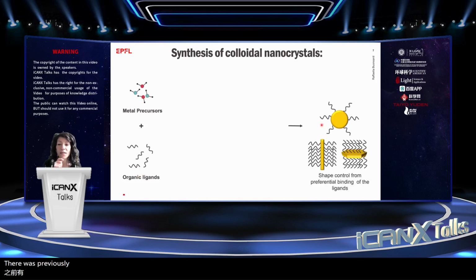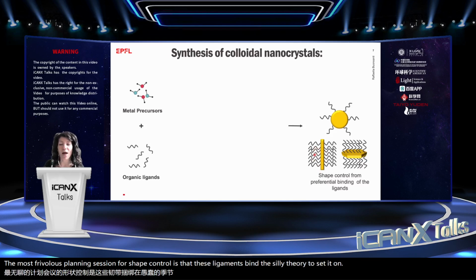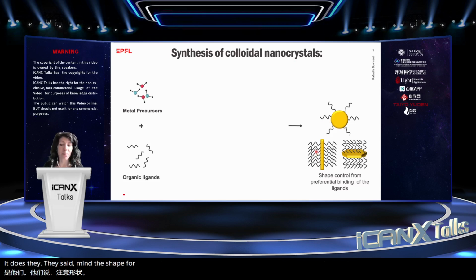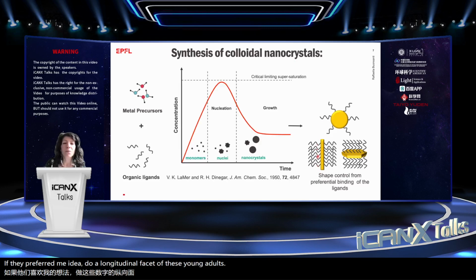The most trivial explanation for shape control is that these ligands bind selectively to certain facets, and thus they determine the shape, for example, as nanorods, if they preferably adhere to a longitudinal facet of this nanorod. In order to explain nucleation and growth, the classical nucleation theory refers to the LaMer diagram, where these monomeric species act as the precursors, and as they reach the critical limiting supersaturation, nucleation occurs and then is followed by the growth.